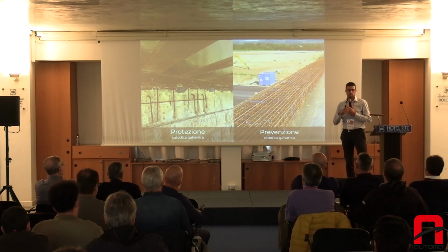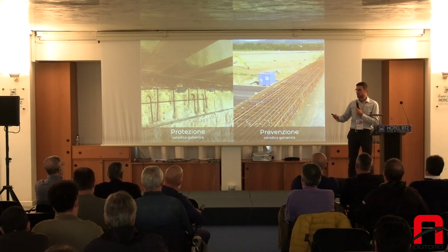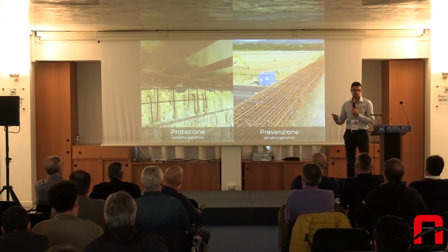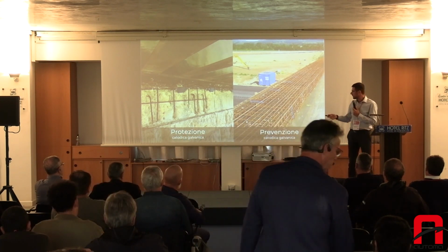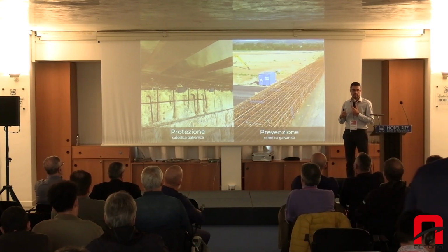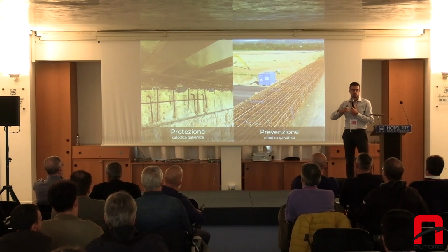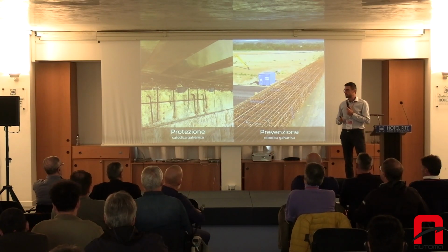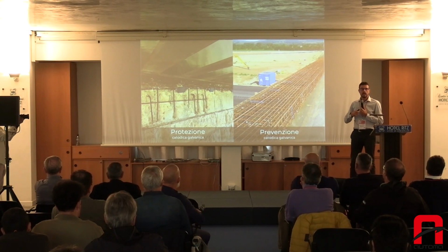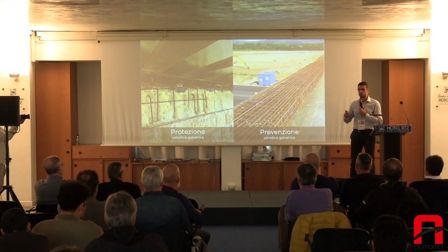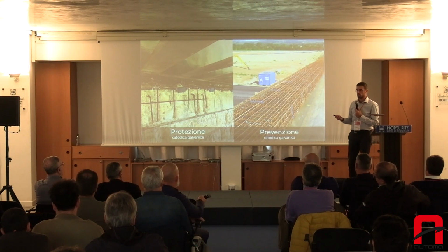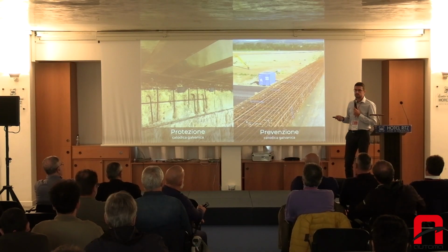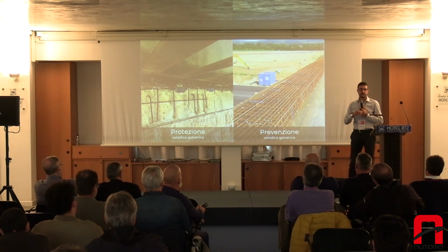We know that steel used for reinforcement bars in an alkaline environment will be protected from corrosion, but with time, this alkaline environment may disappear. So by using this precautionary system, I can avoid the formation of corrosion in the future. In this way, I increase the shelf life of the structure, especially for those structures that need to be functioning for a very long time or when the environment is very aggressive.